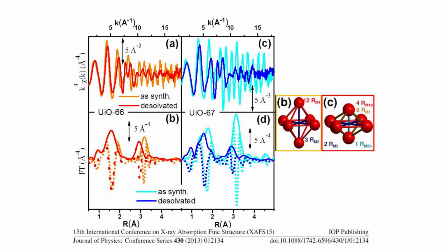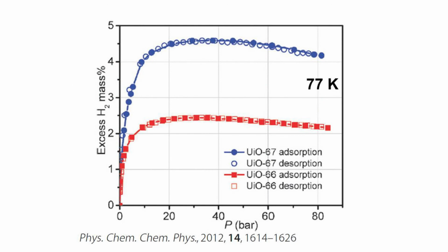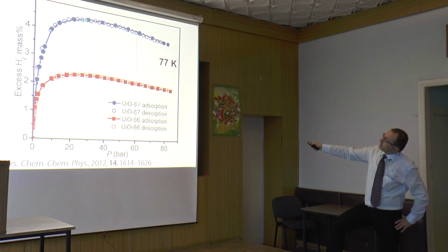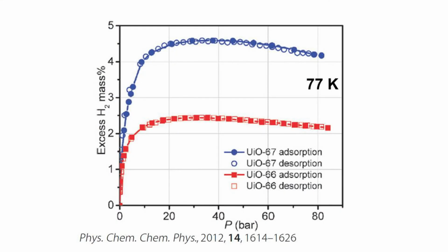We repeat the EXAFS experiment, and exactly the same feature has been observed for this material. Here is the quantitative measurement of hydrogen adsorption, where we go up with this material to more than 4.5% in mass, which is not the record, but it is close to the record.